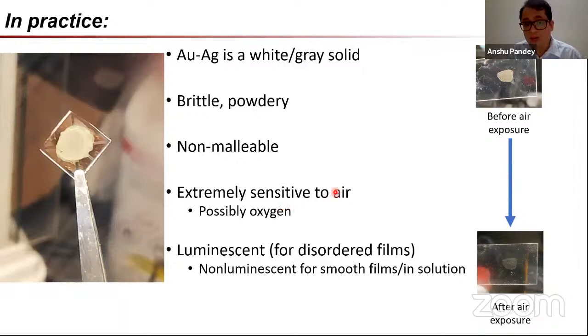This is extremely sensitive to air, which again, gold and silver should not be. Most notably, if you have a white film, you start off white and then it goes black within a few seconds of exposure, where it seems as if oxygen is the culprit here. That's at least our understanding, but again, concrete evidence here is lacking. At least the other constituents of air have been removed from that, but it appears as if oxygen addition is indeed what is happening. There is plenty of chemical evidence to suggest that. These films can be luminescent. This is happening only for disordered films, and this material is otherwise non-luminescent when we are dealing with smooth films. So with that, we have a fairly unusual bunch of properties coming up in this material.